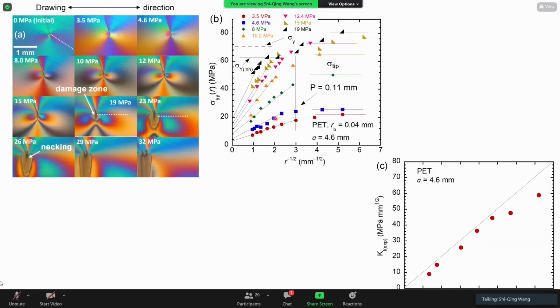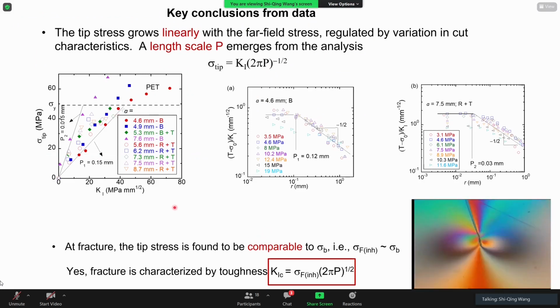In any case, we could look at this so-called fracture mechanical problem purely in the linear elastic region, even for ductile material. So our goal was just to find all the polymers to which we can apply linear elastic fracture mechanics. So for PET, which is ductile, before yielding, before the tip yields, we should still be able to investigate how stress builds up at the cut tip. And you find a similar result. In fact, you could find the experimentally determined K, the so-called stress intensity factor, against the operational K. They are almost comparable in this case, because we use a rather large cut size. So in fact, we can borrow that result.